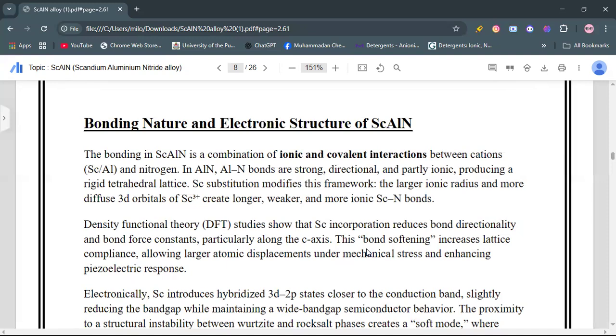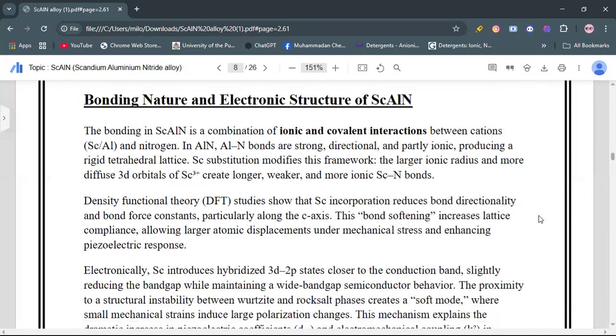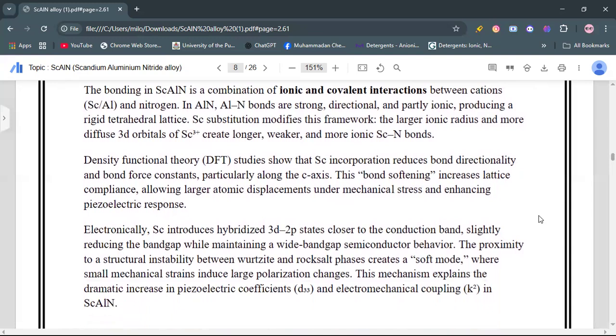As scandium substitutes into the lattice, it modifies this framework. The large ionic radius and more diffuse 3d orbitals of scandium create longer, weaker, and more ionic scandium-nitrogen bonds. Density functional theory studies show that scandium incorporation reduces bond directionality and bond force constant, particularly along the c-axis. This bond softening increases lattice compliance, allowing larger atomic displacement under mechanical stress and enhancing piezoelectric response.